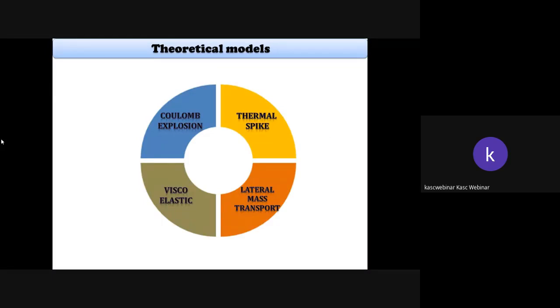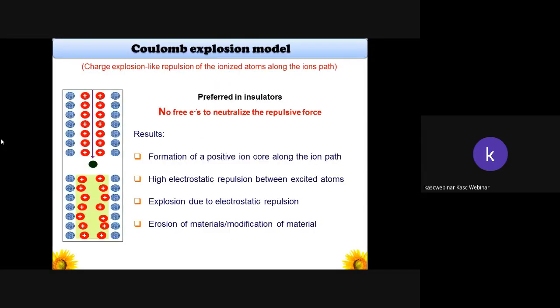Obviously, a number of models are utilized to explain the phenomena that happen inside the material. The first ones are the Coulombic explosion and thermal spike. These two are very dominant while explaining these material properties, and lateral mass transport and viscoelastic flow are also secondary phenomena which support the explanation. And the first one, the Coulombic explosion model. Actually, this Coulombic charge explosion may be like an ionization, a repulsion of ionized atoms at a critical level along the ion path. It may be preferred inside an insulator, so there are no free electrons to neutralize the repulsive forces inside the insulator. So this Coulombic deposition may explode at a certain stage.